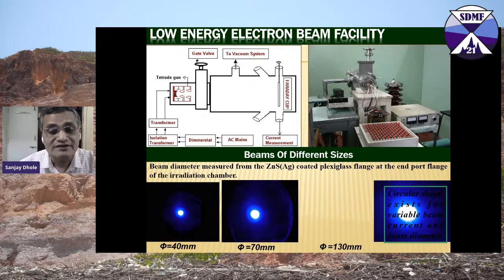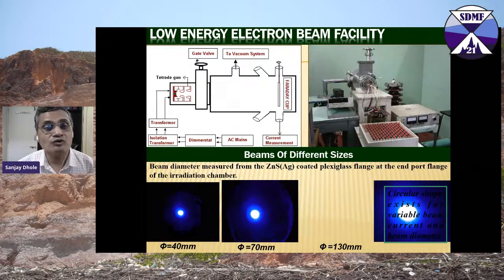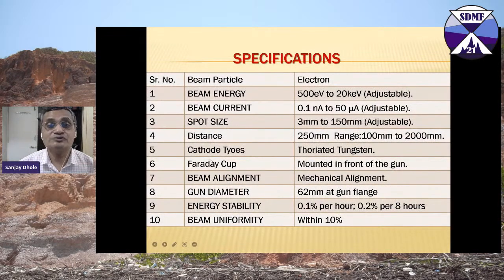And as I said, the energy can be varied from 500 eV to 20 kV. This is the specification: the electron energy, as said, is adjustable from 500 eV to 20 kV. Beam current can go from 0.1 nanoampere to 50 microampere. The spot size can be varied from 3 millimeter to 150 millimeter or so. And the energy stability is very high. The beam uniformity is within 10%.